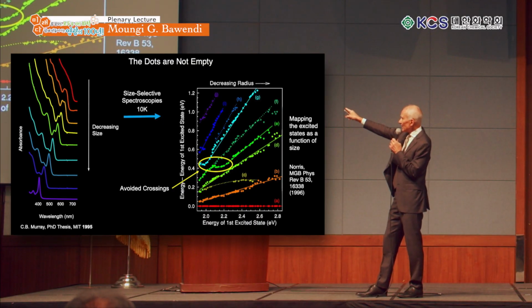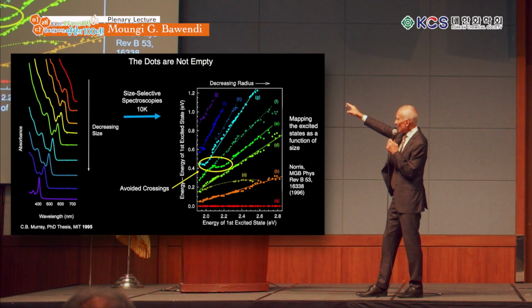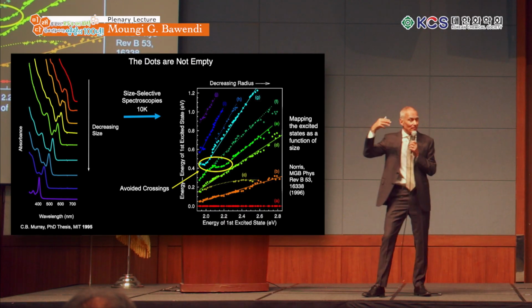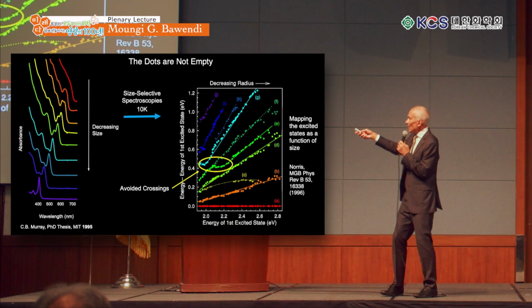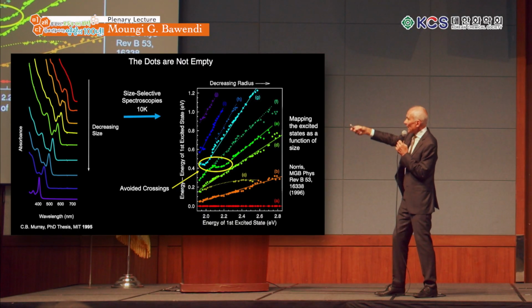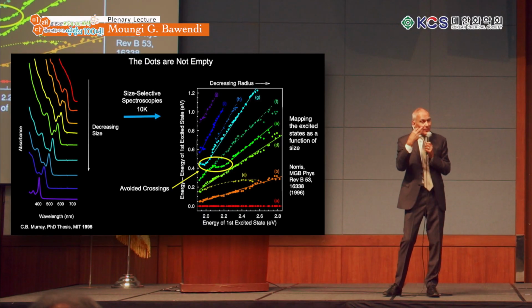And it turns out that this part where the harmonics no longer behave like the particle, like the cavity is empty, it's where the electron begins to be aware that there are actually atoms in the cavity. And it's scattering off these atoms, and it's seeing the spin-orbit coupling, it's seeing the extended crystal structure. And that crystal structure is what we see in the bulk material. And that's the spin-orbit coupling energy between 0 and 0.4 eV here that we see in the bulk material. So that's the first indication that we're beginning to see bulk properties happen.